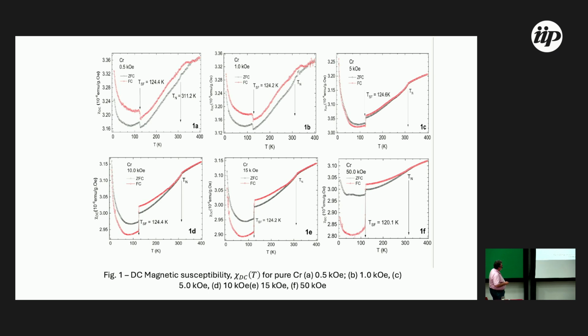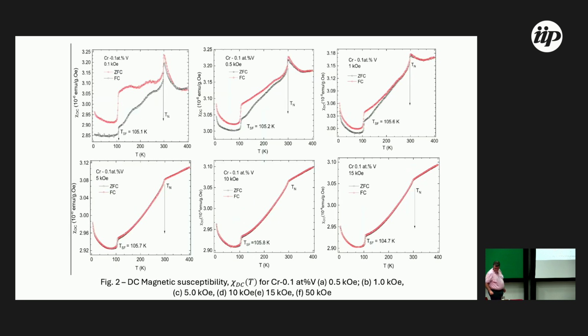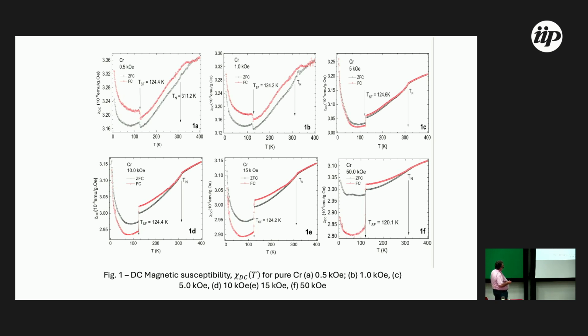The chromium, independent of the magnetic field, shows only Pauli paramagnetism. Observe that when the magnetic field increases, the spin flip transition increases. The black curve is a zero field cooling. I cool down the sample without magnetic field and apply the field at 5K and perform these measurements. In the field cooling, the red curves, the sample is cooled down with an applied magnetic field.